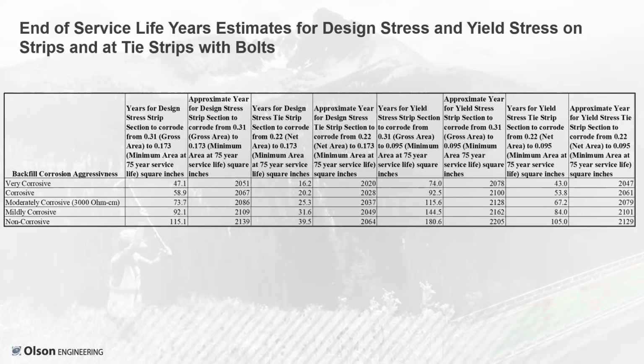The next part is to corrode down to the minimum area, meaning to get down to this 0.173 inch at 75 years service life. And so we've gone through that. And if we get to the yield stress, let's just jump ahead a little bit to the right, since that's the one, it's the ultimate failure.